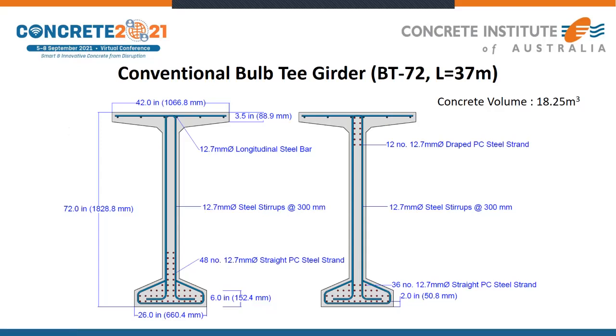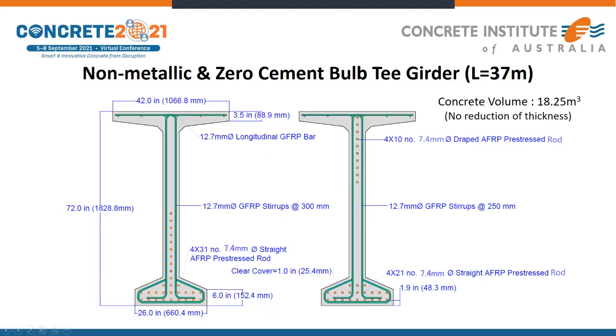We check the CO2 emission. In order to check the CO2 emission, we calculate a very typical beam. This is an AASHTO girder. The span length is around 37 meters. This is the cross section using conventional steel reinforcement. And the concrete volume is 18.25 cubic meters. And this is the cross section using non-metallic technologies, with 7.4 millimeter aramid rod. And also, of course, the strength of concrete is higher, but in this case, I didn't make a reduction of the thickness of the concrete, though we used the same thickness as the conventional T type.